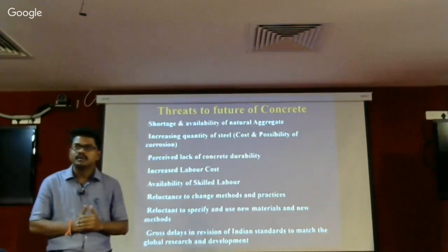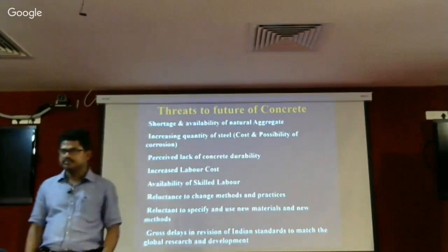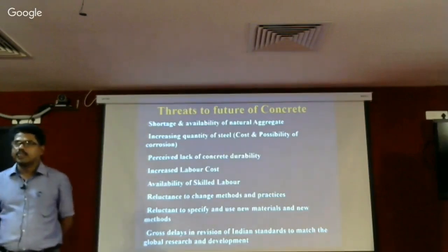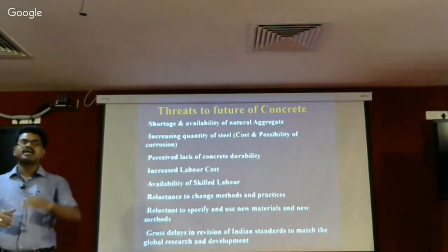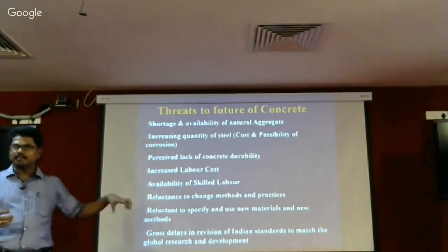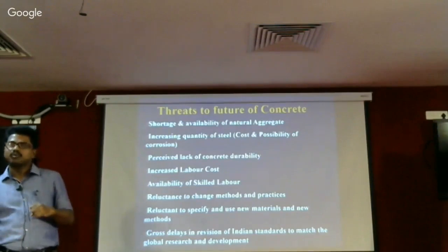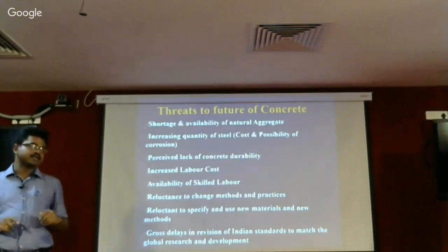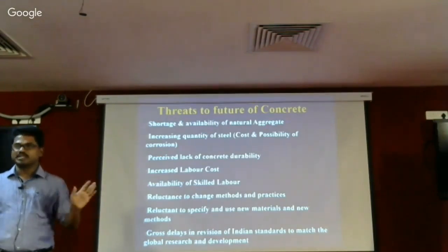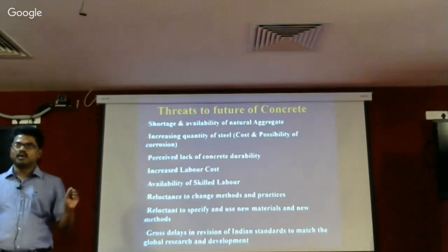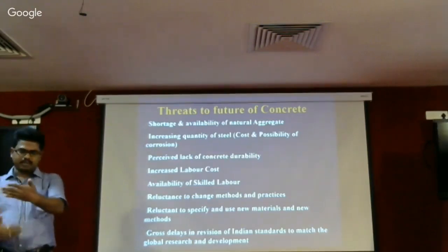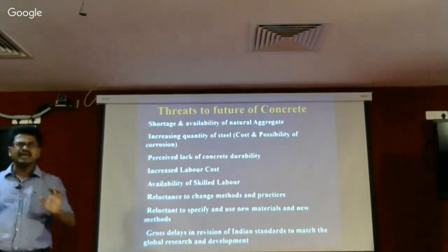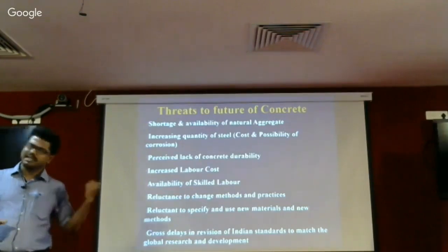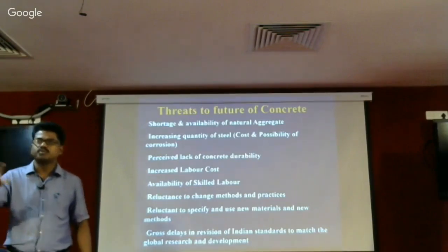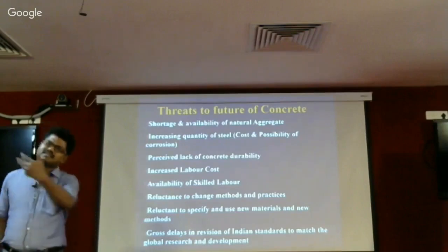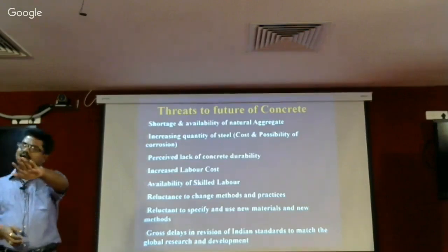PPC cement already has fly ash added. Yes, but in practicality, what type of cement are you using, whether it is OPC or PPC? Yes, I am explaining that. When I am doing experimentation in the lab, definitely I have to take OPC and decide the optimum dosage of fly ash. But in regular practice, nowadays everywhere you are getting PPC only. On the PPC cement bag, they mention that 20 to 25% fly ash is added. That is sufficient if you are going up to M40 grade of concrete.